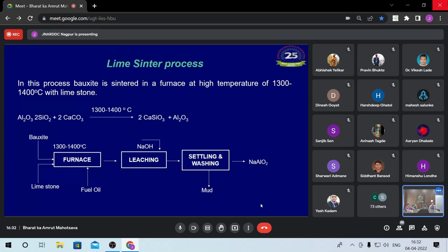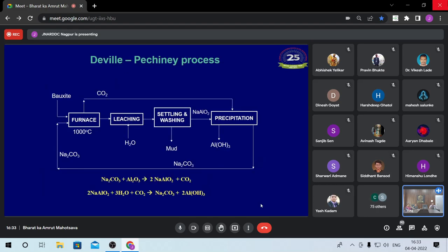This was carried out by heating the bauxite with limestone at 1300 to 1400 degrees temperature, giving calcium silicate and giving the alumina, which was then leached out with sodium hydroxide to give sodium aluminate. After the residue material is settled out, you get the sodium aluminate, and that sodium aluminate is then precipitated to get alumina trihydrate. But this process was not successful because of the high temperature required for the processing of this type of bauxite. Then there was the Deville-Péchiney process.